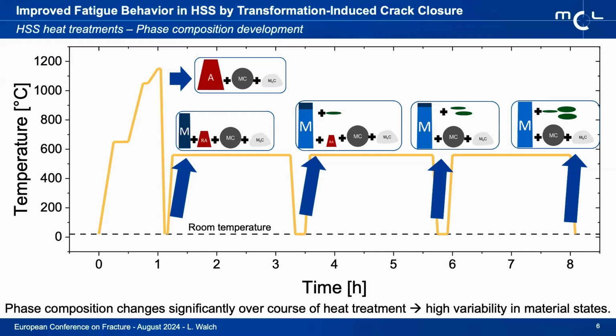So what we tried to look at was the general heat treatment process, which is complex enough in and of itself. As you can see here, there's quite a change in the phase composition during that whole treatment process. One of our approaches was to just try to retain a bit of the austenite that's usually intentionally removed during the tempering heat treatment itself. We tried to retain that until after the heat treatment and see what it would do with the fatigue behavior.